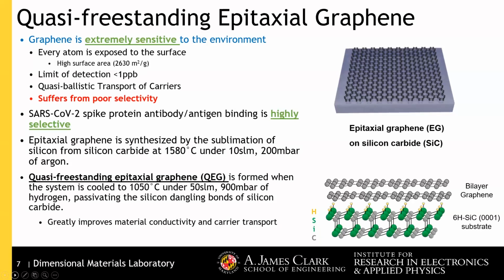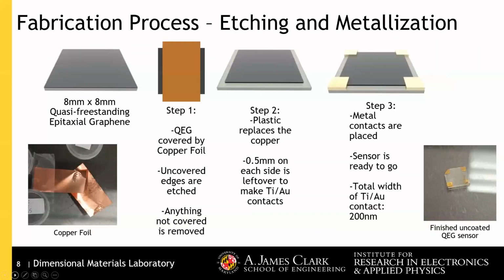And this is a structure of bilayer graphene. So you have the 2 layers of graphene here. You have the substrate, which is this block that it sits on, and that's how we get a more sensitive and more effective graphene. So this is what I did during the summer. First off, in order to get the sensor, we get our graphene, and then we do a process that's called etching.